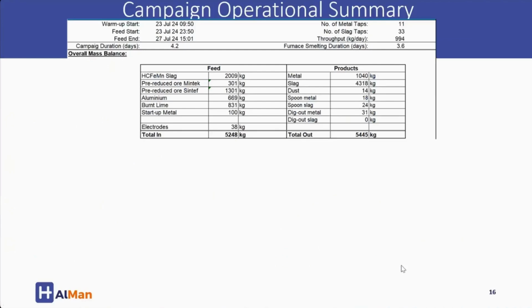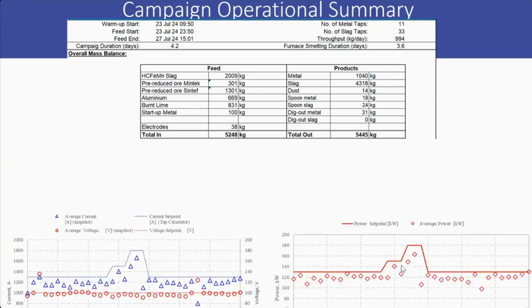The campaign was run over a period of 4 days. We had 33 slag taps and 11 metal taps, and we managed to produce about a ton of metal and 4 tons of slag.